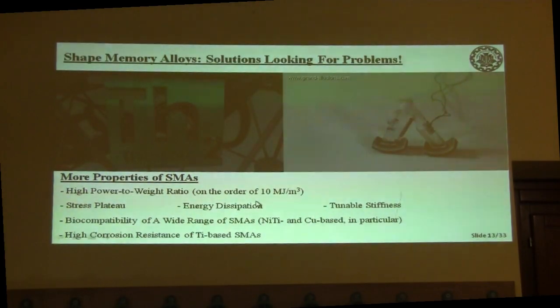Energy dissipation, I call them. They are inherently dampers. I can put them in some parts of some building and can apply them as some inherent dampings. I briefly talked about tunable stiffness. Since austenite and martensite have different stiffnesses, by adjusting the level of stress, strain, and applied temperature, I can tune the stiffness of the whole structure, and this is beneficial.